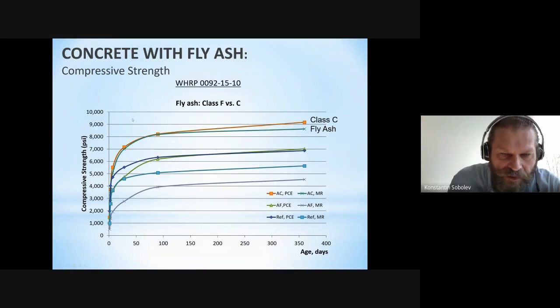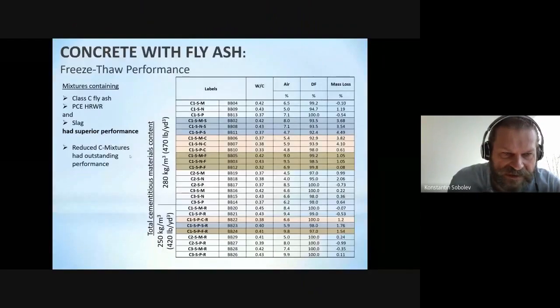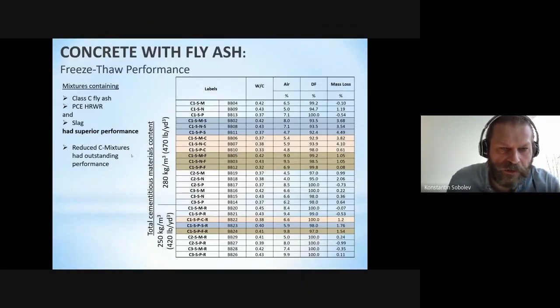And you can see that the reference concrete was considerably improved when we used a modern polycarboxylate-based superplasticizer. So again, the Department of Transportation is happy with 4,500 psi concrete, which is roughly 30 megapascal concrete. But at the same conditions, this can be considerably improved if we simply use polycarboxylate superplasticizer, or it can be improved even further with a combination of polycarboxylate superplasticizer and Class C fly ash. And obviously, strength is not really a big issue. It looks like we know how to handle strength. We know how to improve strength.